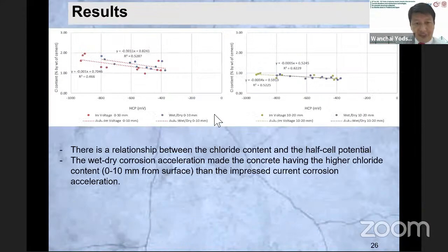And this graph shows the relationship between the chloride content and the half-cell potential. For the left-hand side graph, it is the chloride content at a depth of 0 to 10 millimeters from the surface. And the right-hand side is the chloride content at a depth of 10 to 20 millimeters from the concrete surface. And we can see that there is a relationship between the chloride content and the half-cell potential. And the wet-dry corrosion acceleration made the concrete have higher chloride content, 0 to 10 millimeters from the surface, than the impressed current corrosion acceleration.